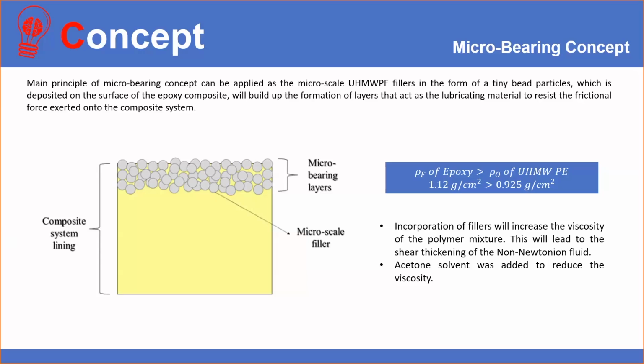So upon curing of the polymer composite, the ultra-high molecular weight PE filler will be turned into a layer of solid lubricant on top of the epoxy composite system. However, other than the density of the components, there are several other factors that will influence the concept, especially upon increasing amounts of filler loading in the epoxy resin.